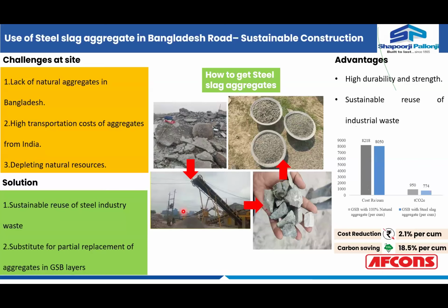Now, there is a lack of naturally available materials in Bangladesh. So in Bangladesh also we used to transport the aggregates from India only, and that adds cost to the transportation and to ensure the suitability of the aggregates. So the idea of using the steel slag, which was available close to Dhaka in one of the industries, was identified and then the suitability of that particular material was tested. Now, it gives you an idea that if you use the steel slag in GSB, the cost of the material reduces by 2% per cubic meter, and the carbon saving is close to 18% per cubic meter in this particular case.